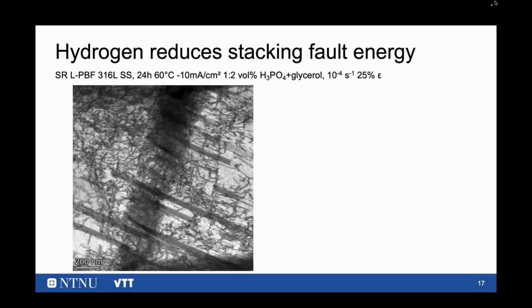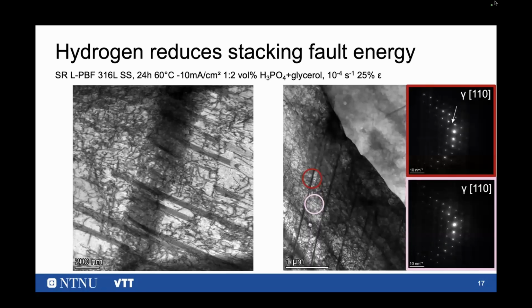We checked in the stress relief condition whether there was epsilon martensite or alpha martensite present, but we could not find any. We saw a lot of defects here: the dislocation cells that are disrupted, nicely aligned dislocation lines, slip bands, and also some stacking faults like here, and the parallelogrammic structure here. We took other diffraction patterns, which showed only austenite.